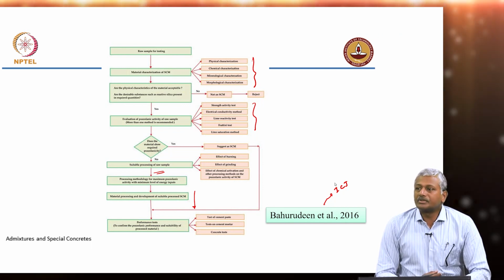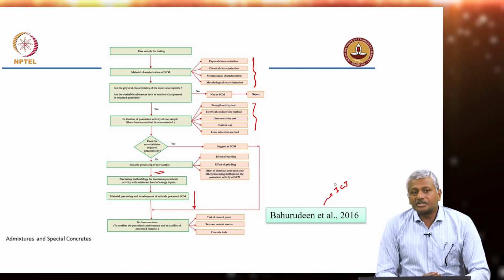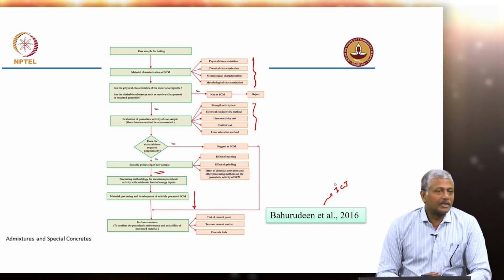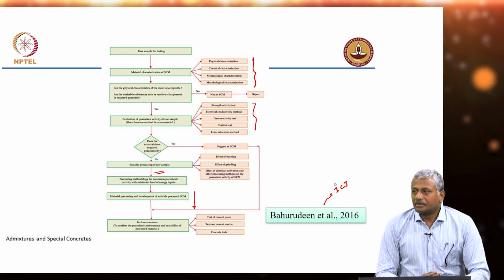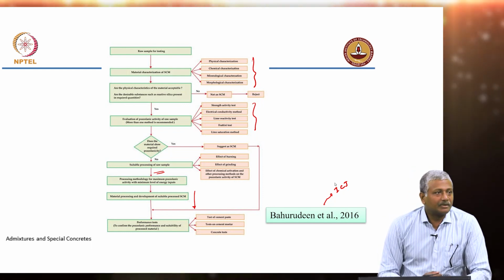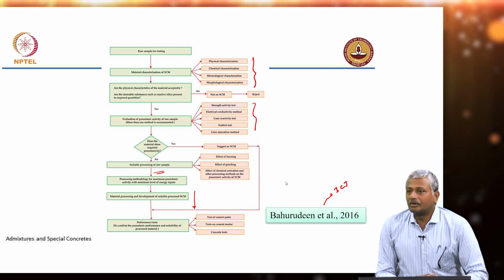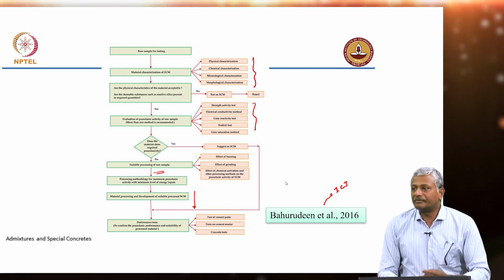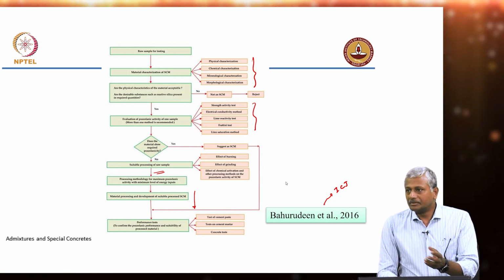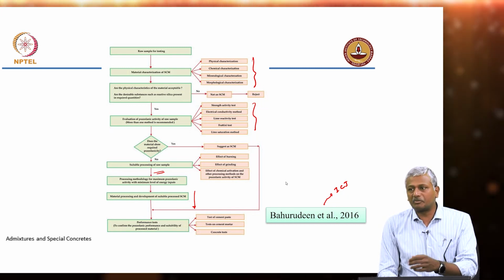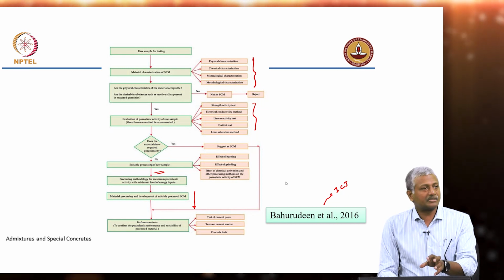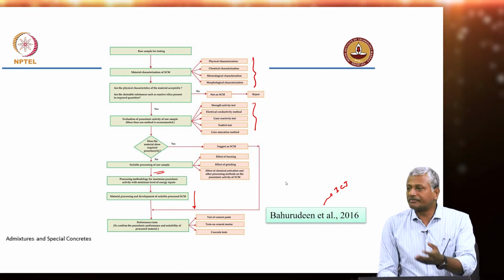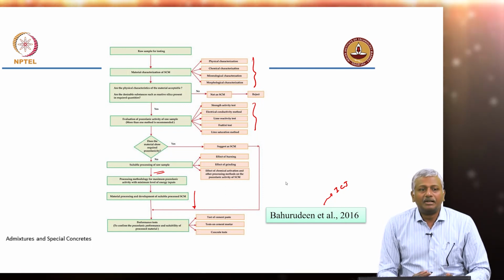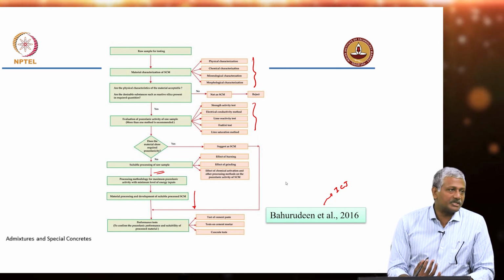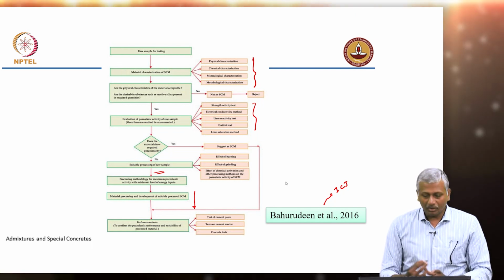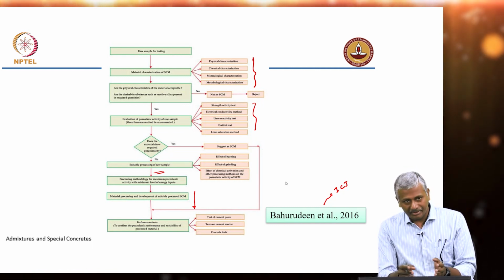Right, we talked a lot about how the cement composition, the type of chemical admixture, the conditions of mixing, the temperature, all of those aspects are actually affecting the way in which the cement interacts with the chemical admixture. Now imagine that you are replacing part of cement and putting in a slightly different mineral or an amorphous material which may or may not have a well defined composition. Composition may be variable, different aspects of the composition may be variable, and so on. And when these materials are used as partial replacement of cement, you may actually further affect the compatibility with chemical admixtures. So one has to be very careful and not just assess the strength development with these materials, but also look at compatibility issues.